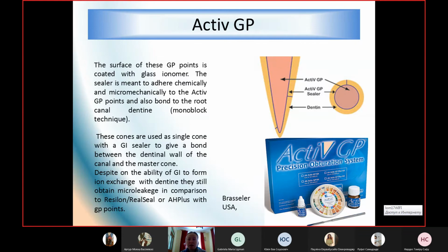it turns out that there is still micro leakage when it comes to active gutta-percha use, because this single cone method is not effective enough, despite the fact that it creates a monoblock. And actually this monoblock technique is very good and very positive. That's why this is a good idea. But anyway, in comparison with other techniques, there was significant micro leakage.